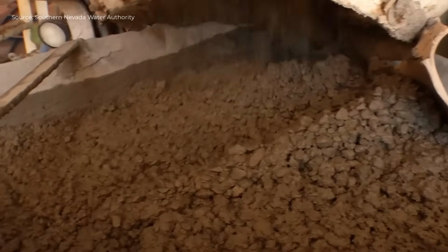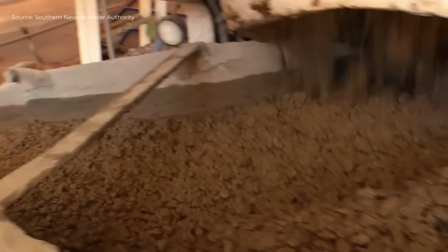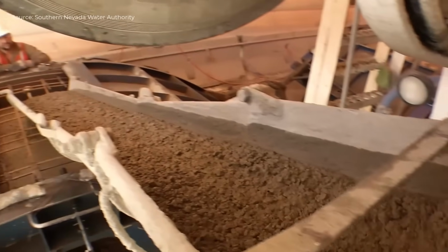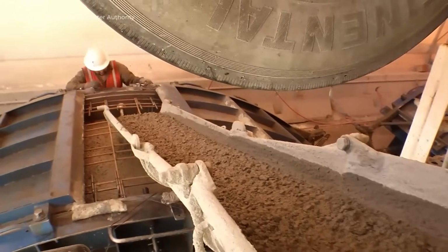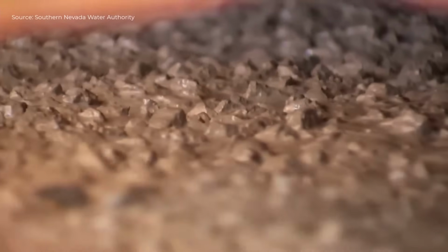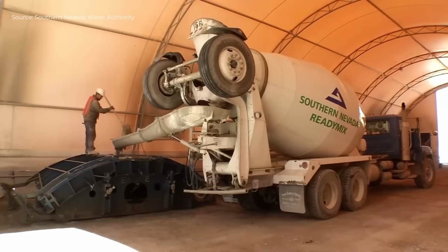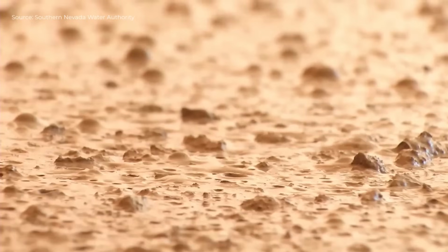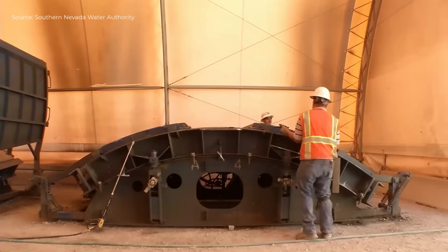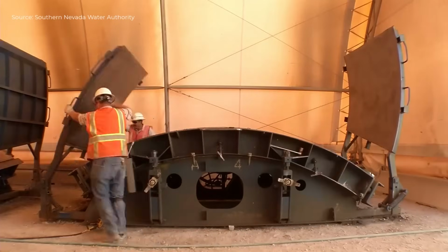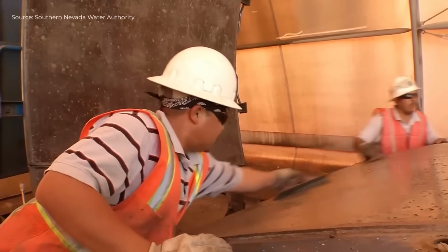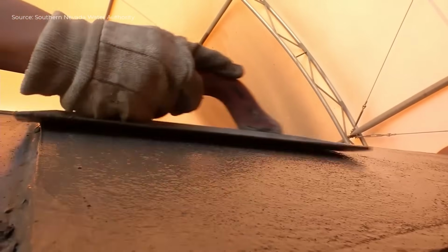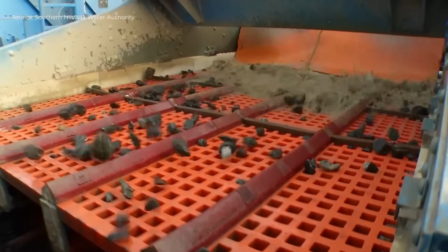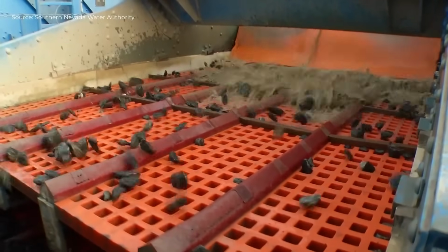The TBM operated in both open and closed modes. In favorable conditions, it used a screw conveyor to move excavated material. In high water pressure zones, it switched to slurry mode, mixing material with bentonite slurry for surface removal. Concrete ring segments were installed every 6 feet to line the tunnel. Over 14,000 segments were precisely cast off-site and placed by the TBM.